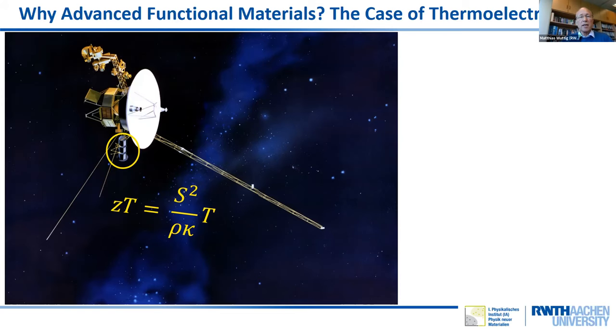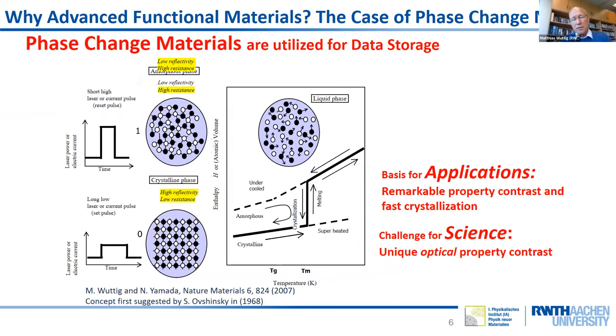There is another interesting application that we have been working on for more than 15 years, and this is phase change materials, which are utilized for data storage. Here you have chalcogenides which you raise above the melting temperature, and then you rapidly quench them down, with quenching rates of the order of 10^9 Kelvin per second. And then you stabilize this liquid-like amorphous state. Interestingly, in these materials, the amorphous state is fundamentally different from the crystalline state in terms of optical and electrical properties. You can use this for optical and electronic data storage, for novel photonic devices, and more.